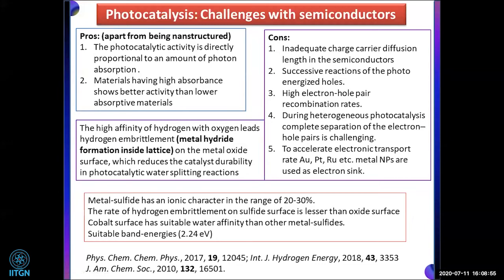This is not happening in case of metal sulfide, because metal sulfides are ionic in character in the range of 20 to 30%. So in this case the hydrogen embrittlement is lesser than in the oxide material, so it should give good stability. Following that, we had not done any photocatalytic study earlier. We have started with this copper cobalt sulfide material. And why we wanted to study it? Because when we do